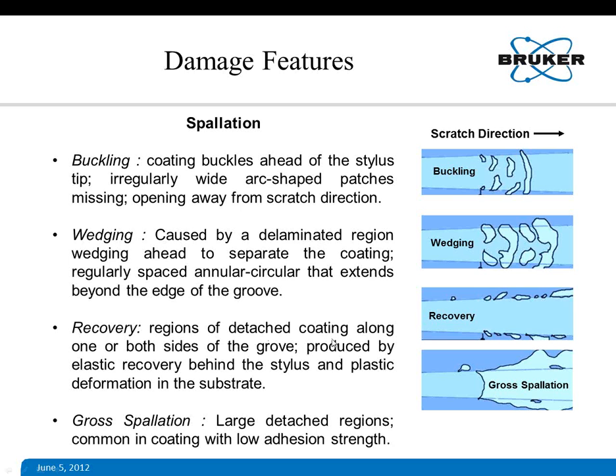Recovery: regions of detached coating along one or both sides of the groove, oriented along the direction of the scratch, produced by elastic recovery behind the stylus and plastic deformation in the substrate. And gross spallation, where large detached delaminated regions of coating occur, where the coating has very low adhesion strength, say ceramic coating on substrate.